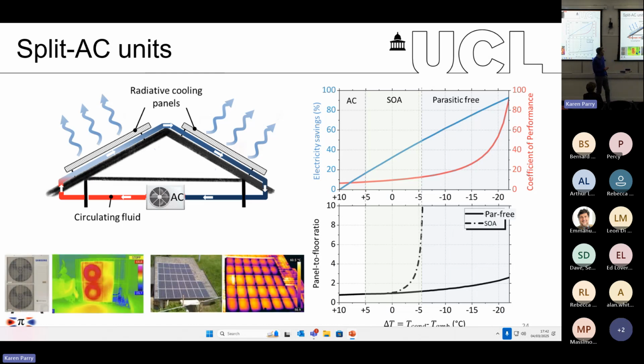Now, what is also very important is that by cooling down the condenser, that's an image of an AC unit, you are essentially removing heat directly from here. So you're also mitigating at the same time the urban heat island effect. And it's way more efficient than having a solar panel powering your AC unit, because a study published in 2024 has shown that solar panels on the roofs of buildings in cities can actually contribute positively to the urban heat island, because they themselves become very hot. So if you have radiative cooling panels, then not only do you mitigate the heat here, but you also mitigate the heat from solar panels.